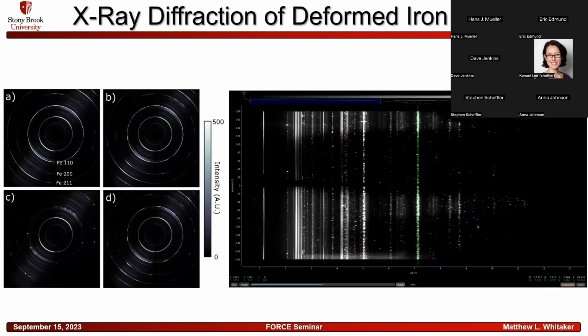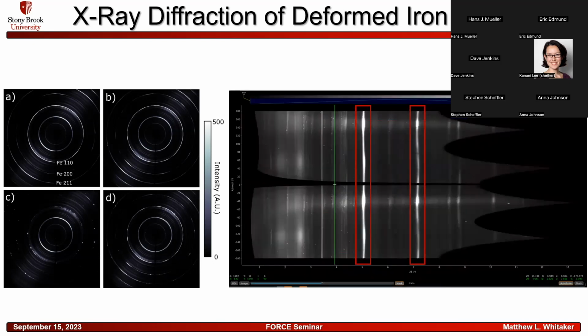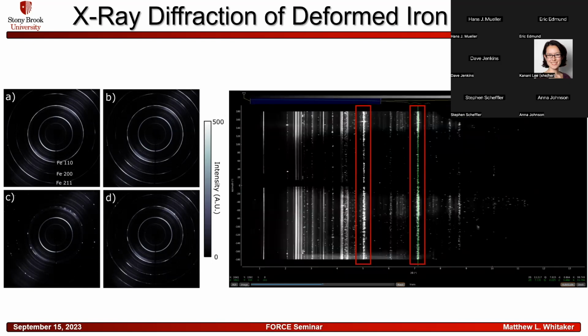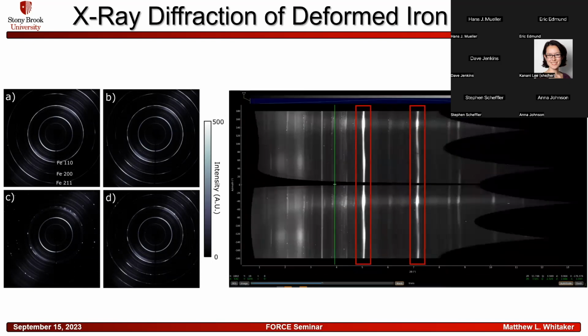And that's what we see here. In particular, I want you to focus on these 2 lines that are shown here. Right now, at high pressure, they are perfectly straight lines, but once we institute that deformation step, you can see that those straight lines become very clear wiggles. And those wiggles are a measure of the ellipticity of the rings once the deformation step is done. So you can see here that it goes very wiggly right there. So this is exactly what we were looking for in the experiment.